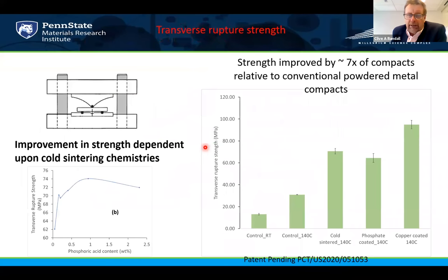All right, so we've actually transitioned some work with manufacturing at 140 degrees in a normal warm compaction system. And we have seen that the transverse stress of the green parts before sintering can be strongly enhanced in terms of the transverse rupture stress. So the cohesion energy between the grain boundaries is improving at least up to 7 times, and we're still pushing this up. Obviously in the fired parts, you're looking at 5 times that number or more, depending upon the chemistry and the microstructures.